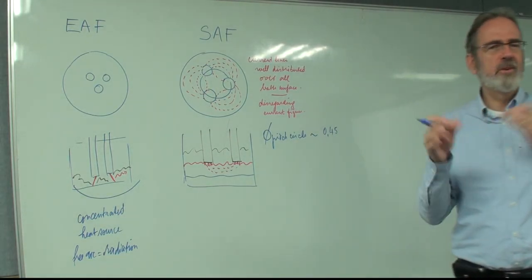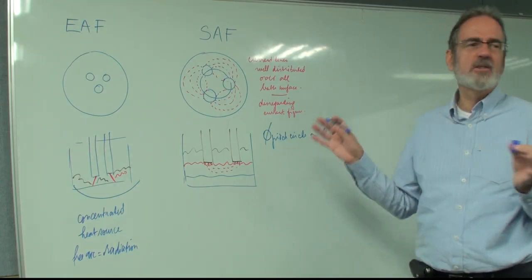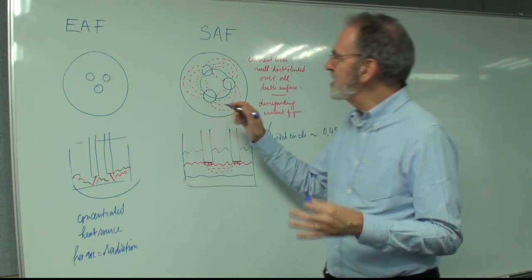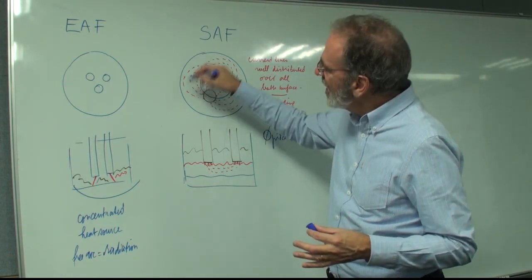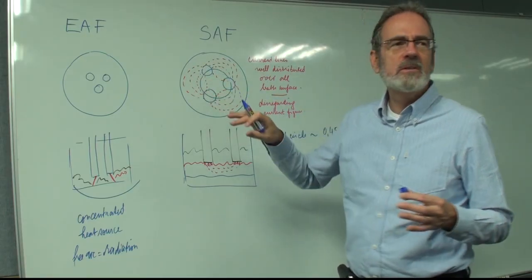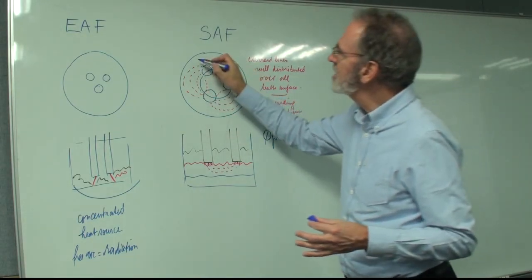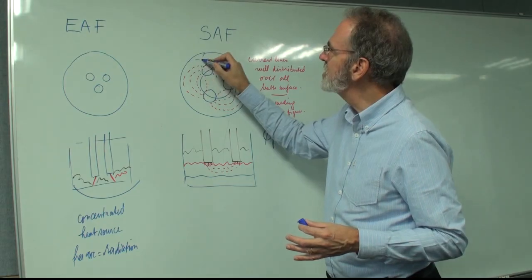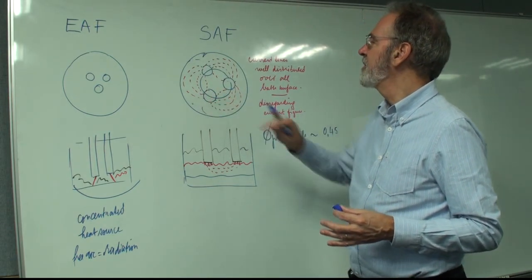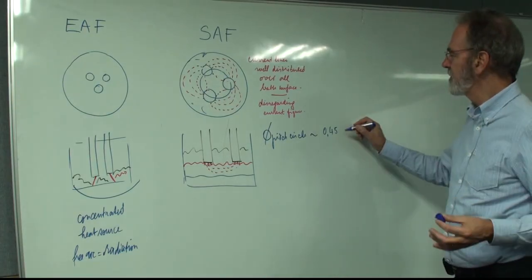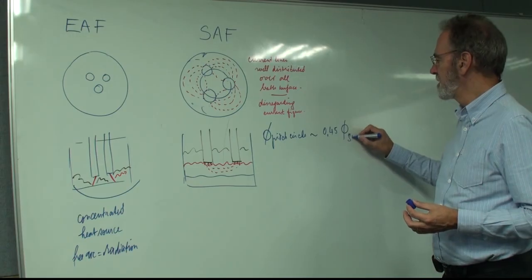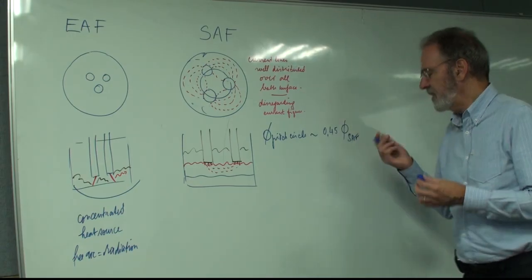I take 0.45. There are discussions. People say it's better to take it larger to have no frozen region. Because here we have a bit frozen region. But roughly.